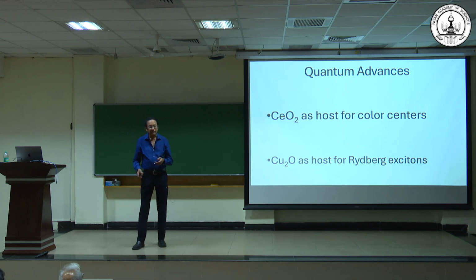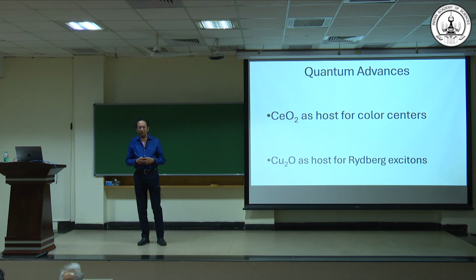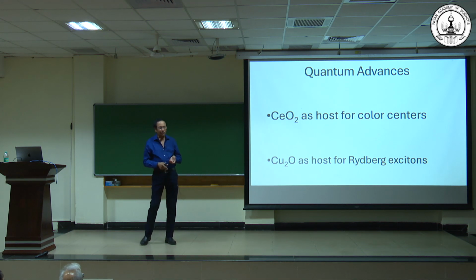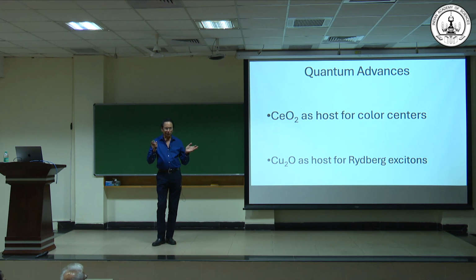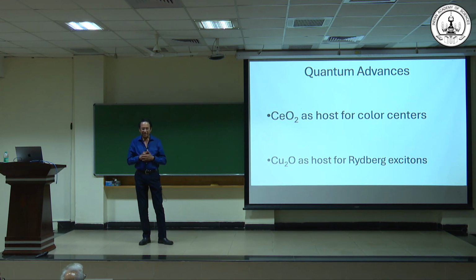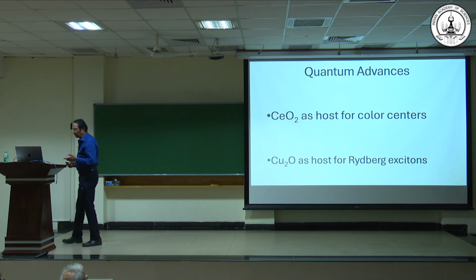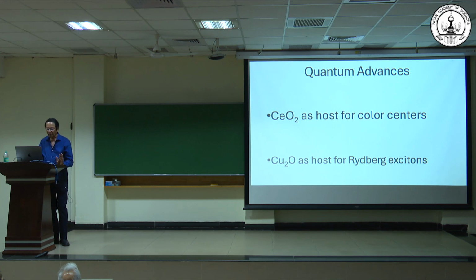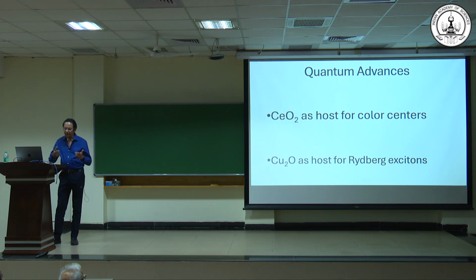So I started looking at the periodic table, saying, what else can we use? It turns out that cerium and calcium are very interesting. These two elements have a lot of isotopes, but they all have 0 nuclear moment, which is really interesting. So cerium oxide would be a fantastic nuclear host. Similarly, calcium oxide would be a very good quantum host. The problem was that calcium oxide is very difficult to make. Cerium oxide, on the other hand, is easy to make. So we now have a big program for cerium oxide as a host for color centers, and we're doping cerium oxide with rare earth elements, and then trying to look for color centers by ion irradiation, creating vacancies in it.